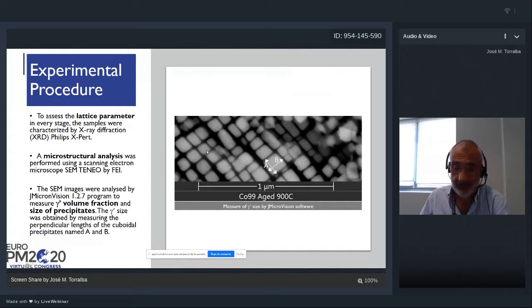Here, more than that, we have assessed the lattice parameter by X-ray diffraction. We have analyzed the microstructure, and also we have measured the volume fraction of the gamma prime precipitates and also the size of these precipitates. We have measured these two dimensions in the square precipitates, and as you see here, the length of the A and B parameters are different depending on the treatment and depending on the sintering temperature.